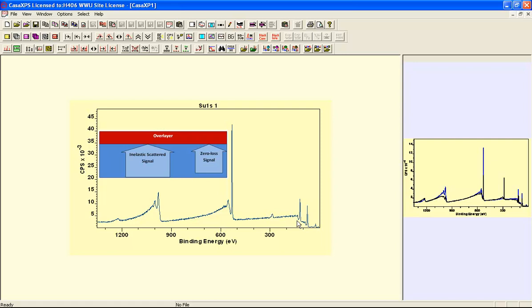So these aluminium peaks are coming from material that is deeper into the surface than this carbon Auger peak down here. And similarly, there's a difference in the sampling depth for the oxygen 1S and the oxygen KLL. So the fact that we see a small peak for the carbon 1S and also a small peak in the right proportion for the carbon KLL suggests that we do indeed have a thin carbon layer that is at the